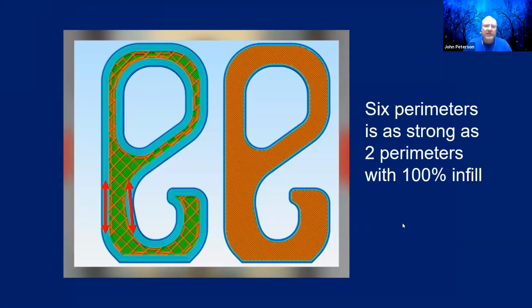So you can see here when he did some testing, he found out, for instance, that if you did 6 perimeters, that ends up being as strong as, I think that's 15% infill, it's as strong as 2 perimeters with 100% infill. And you can imagine how much more time and how much more material and how much more weight would be in this one with 2 perimeters and 100% infill. That's a significant finding here. And it kind of makes sense too.